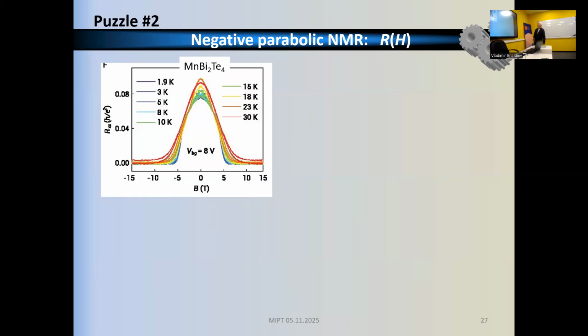The first puzzle is in transport. Actually, this is a more general behavior, which is intrinsic to a large variety of van der Waals type antiferromagnetically ordered materials. For example, this famous MnBi2Te4, and all these materials show negative magnetoresistance like this. It's not large, about a few percent, and it develops exactly correlated with magnetization.